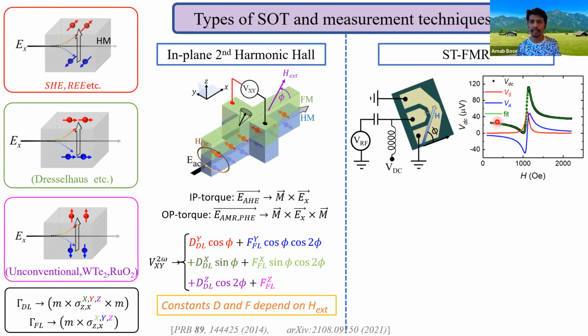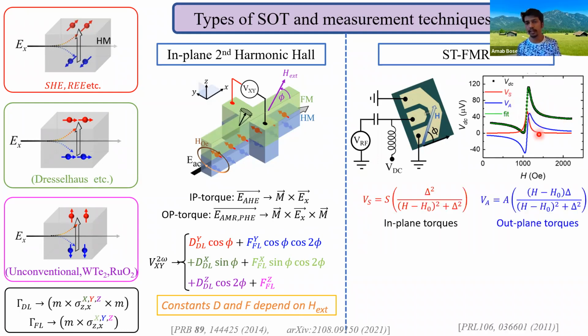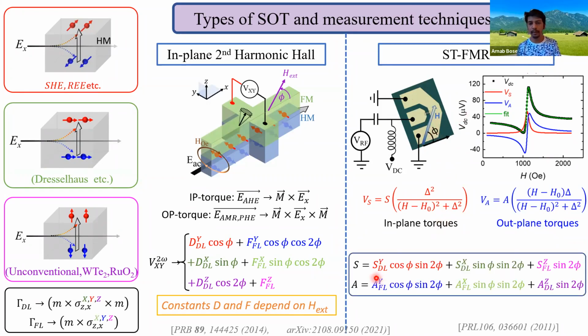So this is a typical STFMR DC voltage spectrum. This can be fit using symmetric and anti-symmetric Lorentzians. From the symmetric Lorentzian, we get all the information about in-plane torques. And for the anti-symmetric Lorentzian, we get all the information about out-of-plane torques. Now we repeat the experiment for different values of phi to get the angular dependence of the symmetric and anti-symmetric components. From this angular dependence, again, we can identify and also quantify 6 different types of torques, 3 different types of damping-like torques and 3 different types of field-like torques. So these are the 2 techniques that I have implemented in this current study.